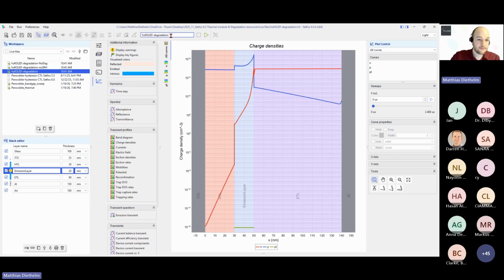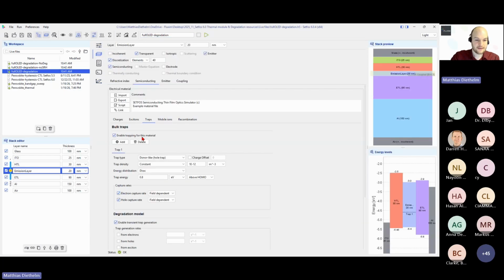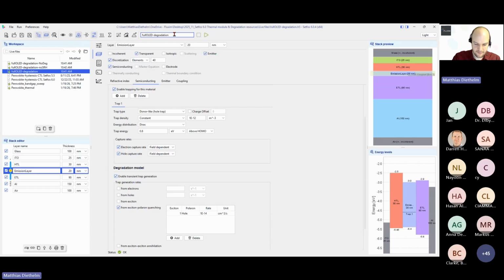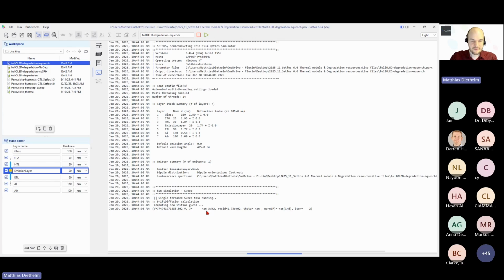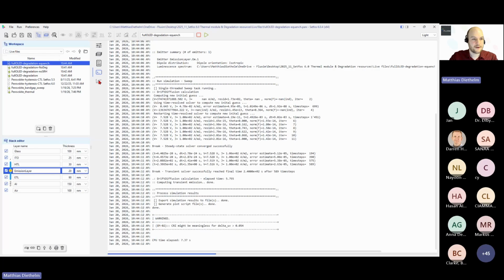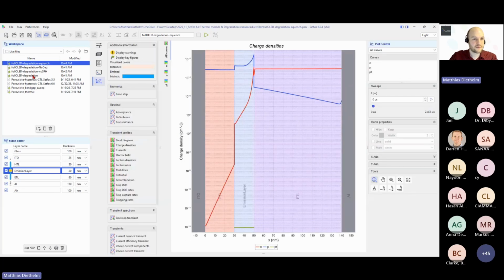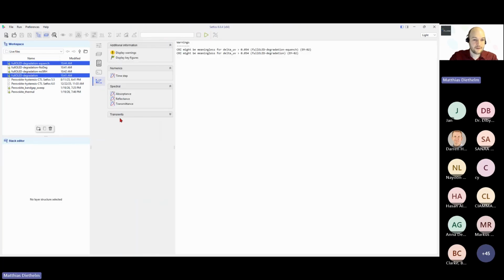The last interesting change is, of course, you can have a look at different models of what effects or factors are leading to trap sites. So instead of hole polaron, I choose now electron in combination with excitons to lead to trap states, and to have a look at how the luminance curves look compared to the hole-exciton or polaron-exciton quenching.